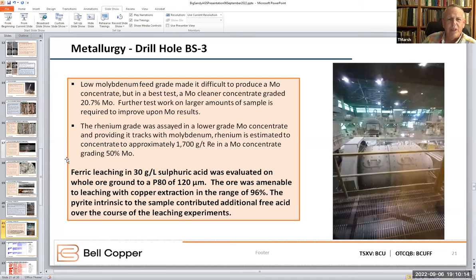But I really wanted to know what's the rhenium grade. If we move 1.2 kilometers from that nearly 1% rhenium that we saw in BS1, what's the rhenium grade in the molybdenite? And they said, hey, if we could make a 50% concentrate out of what you gave us, it would grade approximately 1,700 grams per ton rhenium, or about 0.17% in a typical moly concentrate grading 50%. So it gives us hope that once we get out into a more moly-rich environment, rhenium will be an economically significant part of what we're finding.